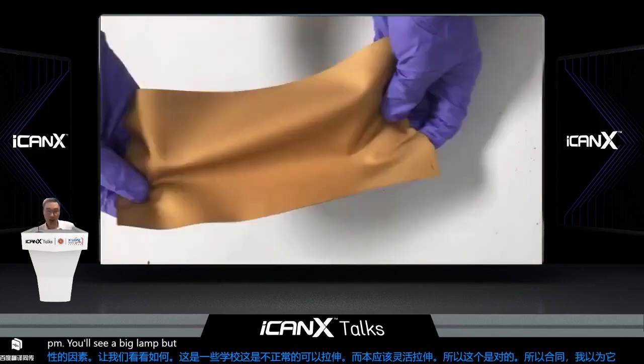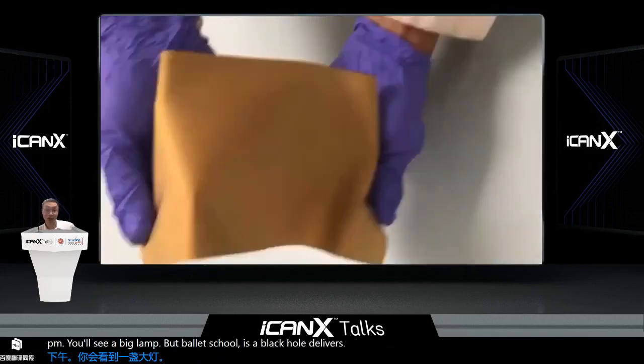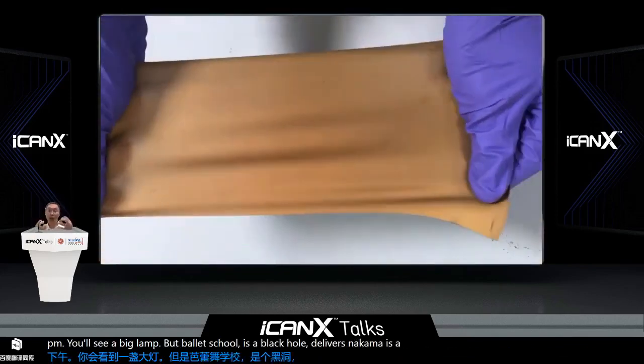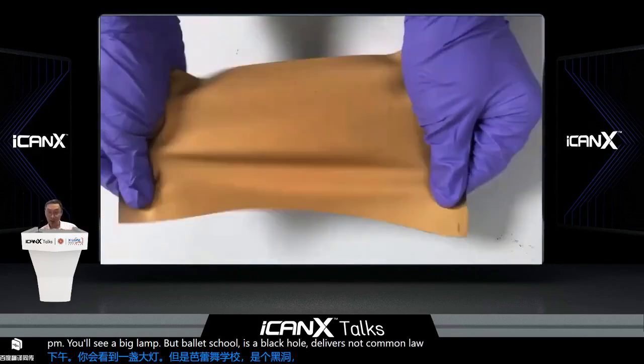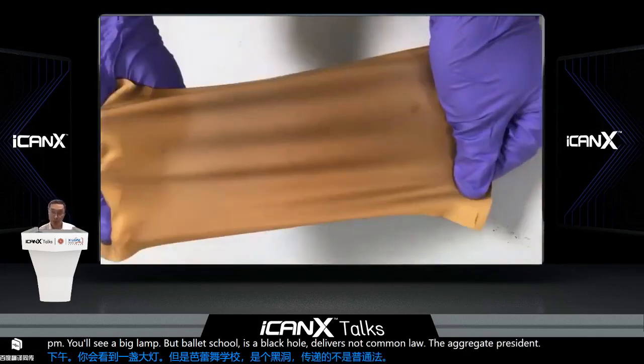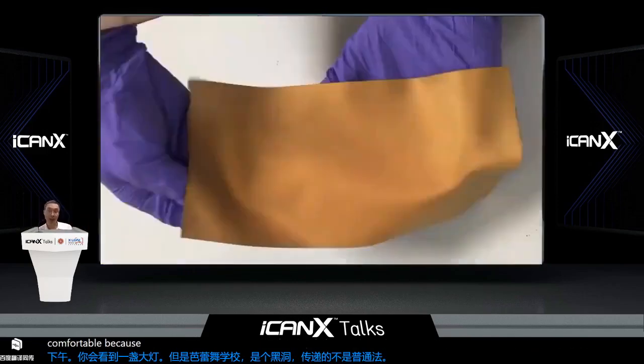And you'll see the back layer. The back layer is black in color. Do you know what makes it black? It's not carbon, it's gold particles. The gold nanoparticles aggregate together, and because of surface plasmon resonance, the band will redshift, and with more contact it becomes black in color. So this is how it works.